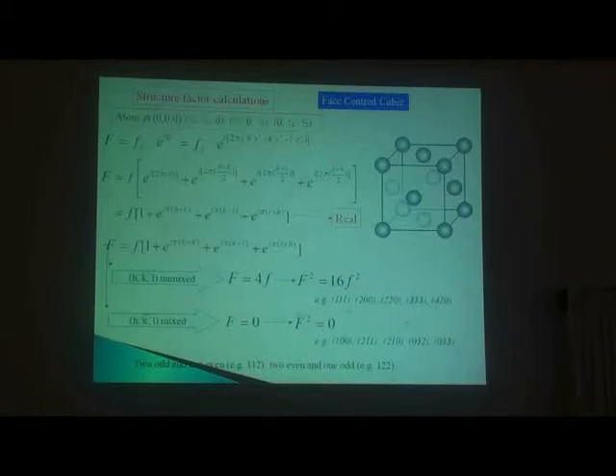Every face is centered. So you have three more positions, this and this. When you calculate the structure factor, you get 1 for the first, then h plus k, k plus l, and l plus h. When you have mixed values, even and odd mixed together, one of them will be positive, the other will be negative, so they cancel. If they take all even or all odd values, they will remain. Therefore, you get maximum scattering. If they are mixed, then you get 0. That is why 1 0 0, 2 1 1, 2 1 0 and so on will be missing in the pattern. You will wonder why this is happening. Okay? This is the condition.